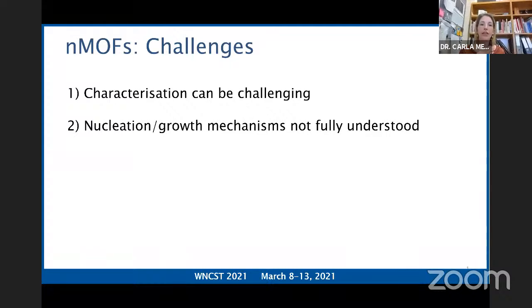First of all, the first challenge is that the characterization of nano-MOFs can be quite challenging. Their submicron crystal size is too small in many cases for structure determination by conventional X-ray crystallography techniques. They're also prone to beam damage using electron microscopes. And then the second of several challenges, but the second one I'll mention today, is that the nucleation and growth mechanism or mechanisms of nano-MOFs really remains far from being fully understood. And without that, the reliable production of MOF nanocrystals will continue to remain elusive.